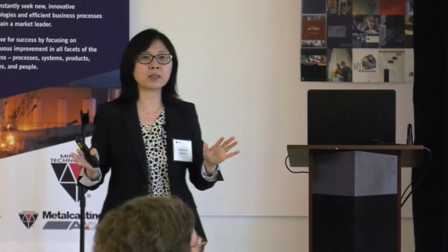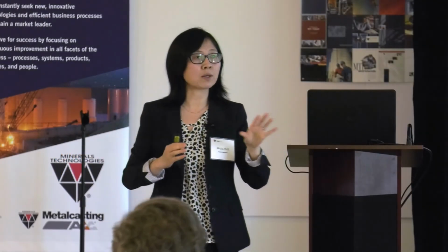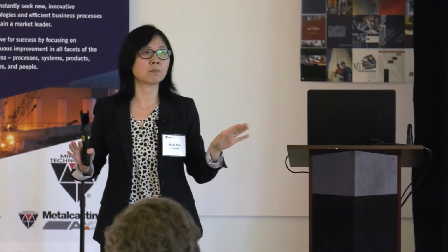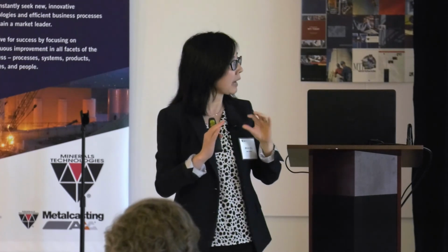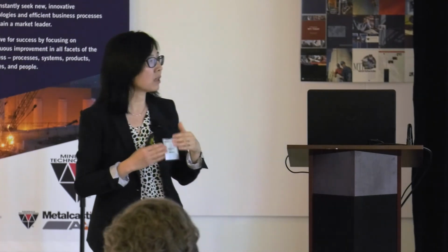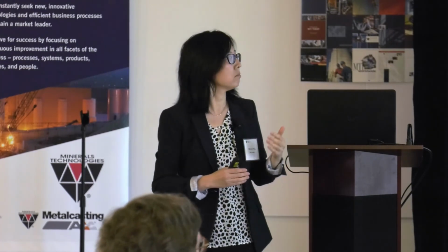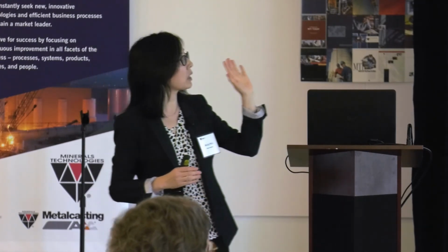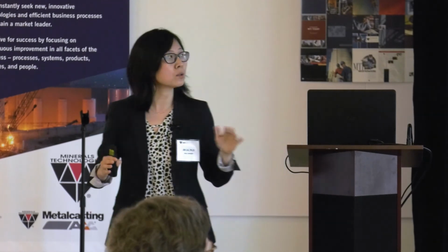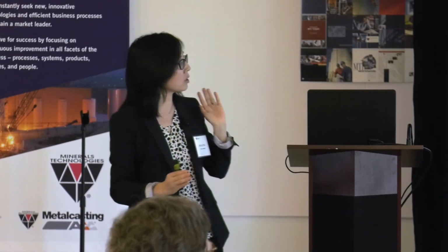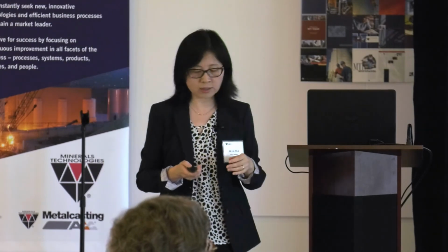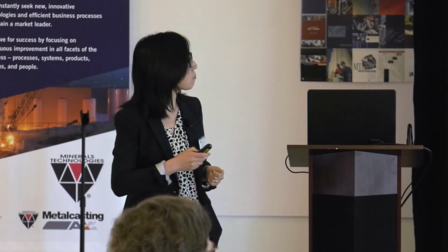But if you are familiar with treatments using GAC or activated carbon, 100 milligram per liter basically is going to kill the carbon. It's going to block the pores for GAC, and the efficiency is going to be reduced by 10 times or more. So in the future, we're going to try to do a comparative assessment under the same conditions to see how much GAC would lose capacity relative to FLUORO-SORB 200.